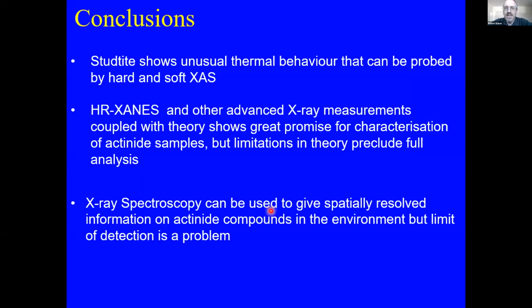That concludes what I wanted to tell you about, showing that studtite has unusual thermal behavior that we can probe by both hard and soft X-ray spectroscopy. This high energy resolution XANES and other advanced X-ray measurements, coupled with theory, shows that we can really drill down in depth at the electronic structure of these. But we're limited now by the level of theory that we can attain. And we can also use X-ray spectroscopy to give spatially resolved information on actinide complexes under environmentally relevant conditions.